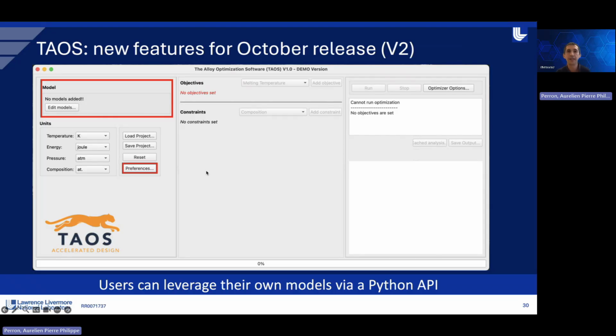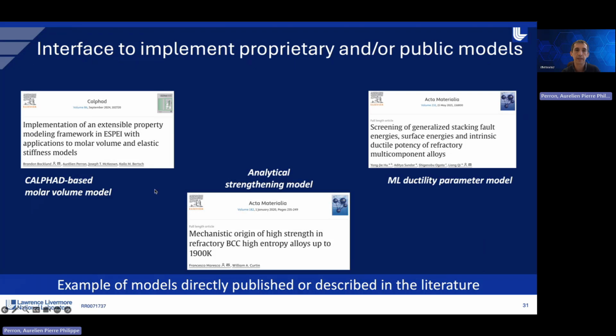So let's start with the bring your own model feature. So the GUI is slightly different for the V2, so the release is scheduled in October. Now you will be able to leverage your own model via a Python API. So how did we do that? It's because you have, for instance, a lot of models in the literature that you could leverage, or you can have your own proprietary model that you don't want to publish, but you would like to leverage for an alloy optimization. So for instance here, what I'm highlighting is a recent paper from our group that published a CALPHAD-based model for molar volumes. There are also papers in the literature, analytical models for yield strength of high entropy alloys, BCC ones, but also machine learning models where you can estimate ductility of this class of materials.